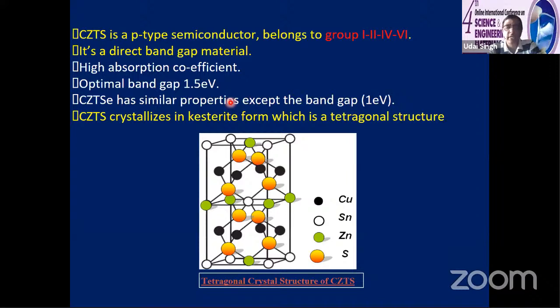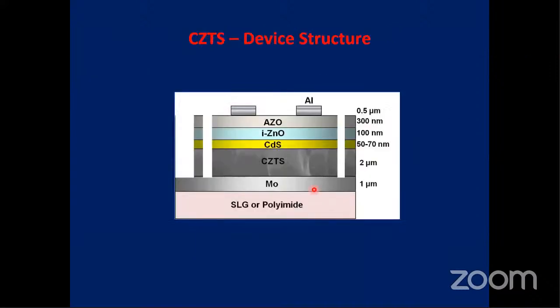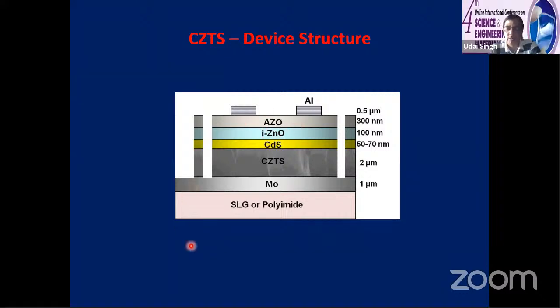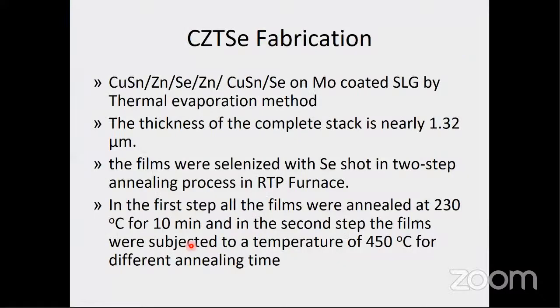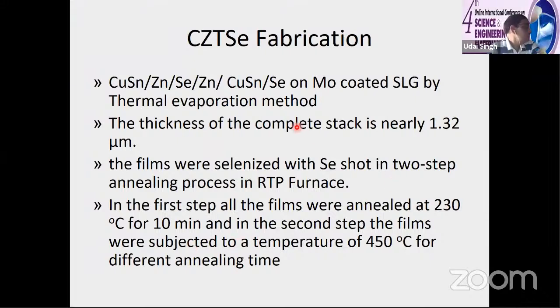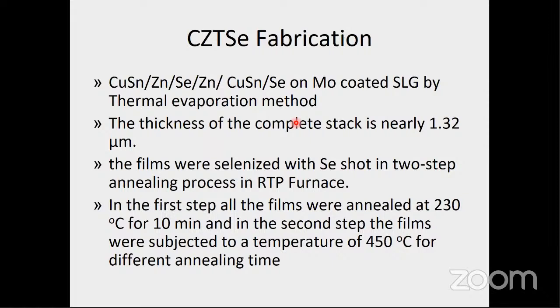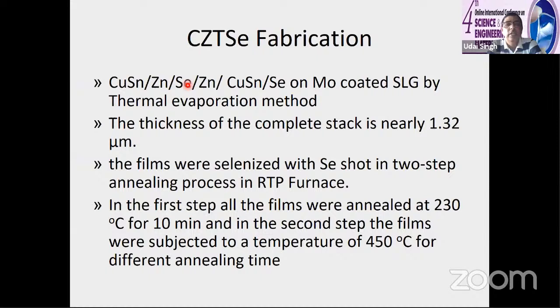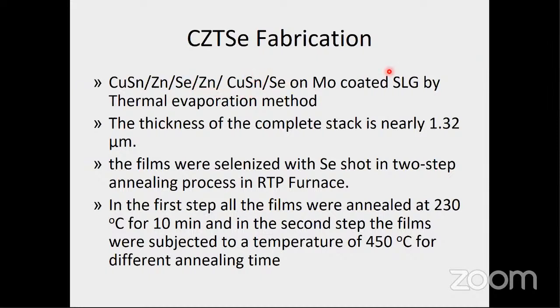Material property is the same as the CIGS. The device structure, I told you, is the same: CZTS, CdS, IZO, and Ag. So in our lab also we have tried to make this copper zinc tin selenide fabrication. We have used copper tin, then zinc, then selenium, and then zinc, then copper tin.